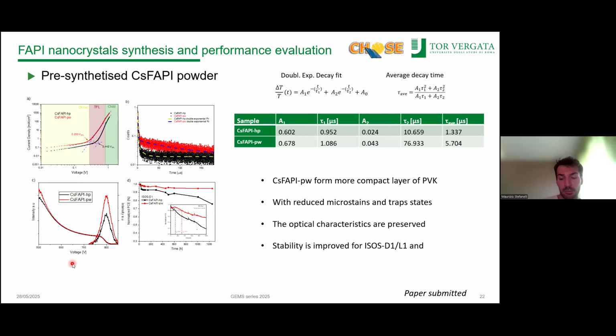So the compositional part is controlled quite carefully, and also the stability is improved for our FAPI from powders. The results are good for the ISOS-D1 test, that is the shelf life, and also for the light soaking test. Especially for the light soaking test, I don't know if it's really visible because it's a bit small, but, let's say, the T80 for our FAPI powder comes at 320 hours after the light soaking, and for our high purity precursor instead the T80 is just at 120 hours.